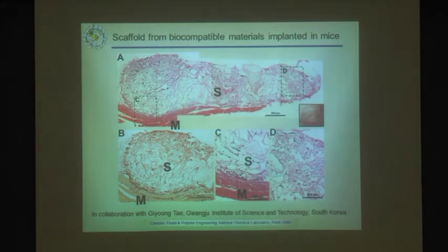What that lets us do is, for example, create materials where the modulus of the material provides cues to the cells and changes the way in which they differentiate inside them. So for example, if you put stem cells into scaffolds with different moduli, you can use this mechanical cue to modulate the kind of cells that they will differentiate into. That's something that we are doing. This is work done in collaboration with somebody who knows a lot more about tissue engineering than we do in our group.